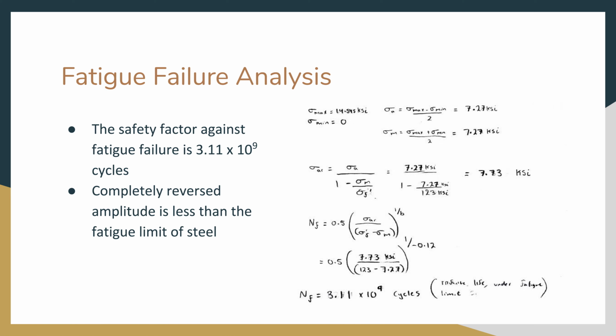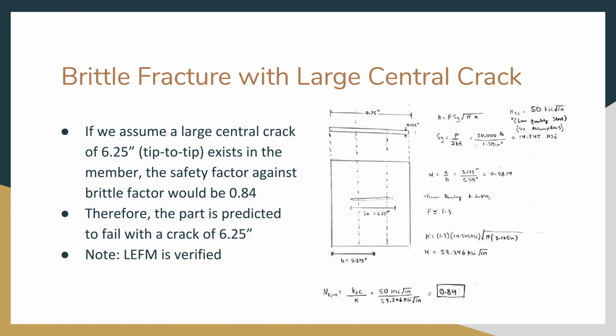Using the property data of steel, it was found that the fatigue failure would be 3.11 times 10 to the 9 cycles, which corresponds to basically infinite life, and this makes sense as the reverse loading amplitude is well under that of the fatigue limit of steel.